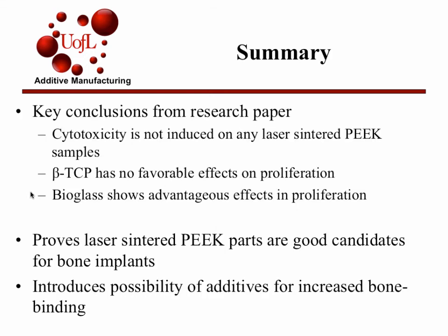So the summary for this paper is cytotoxicity, which just means toxic to cells, is not induced on any laser-sintered PEEK samples, and this is proven by the viability and proliferation tests. Beta tricalcium phosphate from this study showed that it had no favorable effects on proliferation, while bioglass shows advantageous effects.